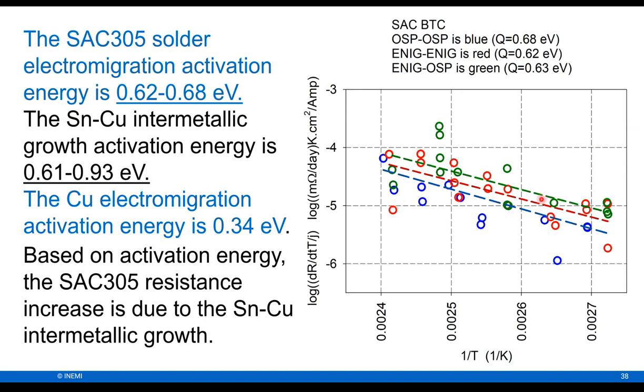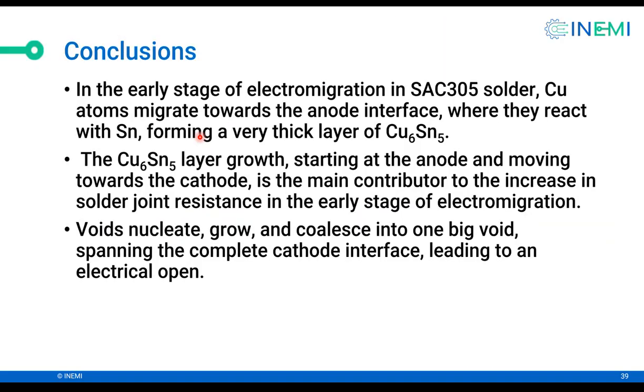So I've shown this plot before, but let me summarize that the slope of the plot gives us an activation energy of 0.6 to 0.7. We also know from published work that tin copper intermetallic growth activation is 0.6 to 0.9. So they're similar values, whereas copper electromigration activation energy is 0.3. So we are saying that the electromigration activation energy has to do with tin copper intermetallic growth. So that's the conclusion.